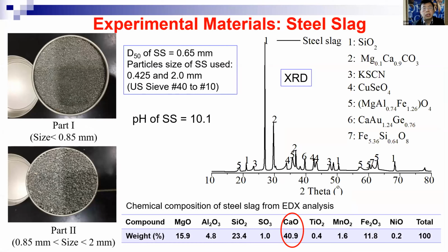First thing, we use steel slag. This steel slag is from one of the local industry steel plants. The particle size can range a lot, but we try to focus on between US sieve number 10 to number 40, so that we can control the size of the steel slag. So we choose part 1 and part 2. Basically, we make 2 groups of the steel slag, the same source, but 2 different sizes, a smaller size and a little bit bigger size. And we also use EDX to see what chemical composition is in the steel slag.